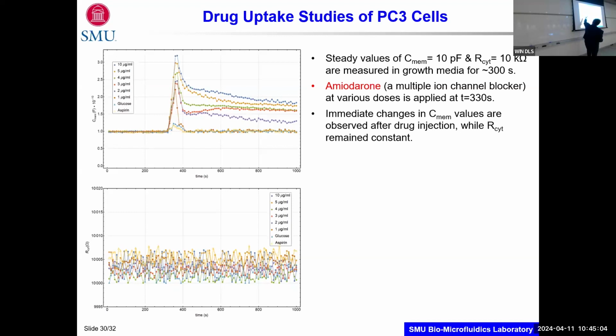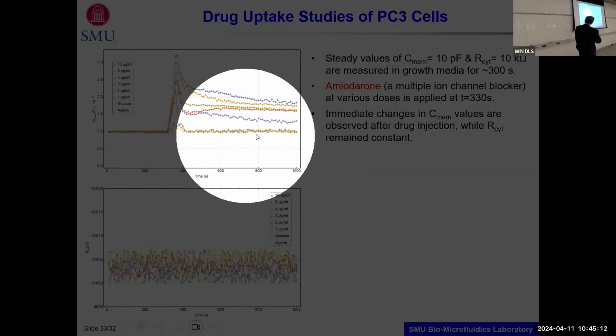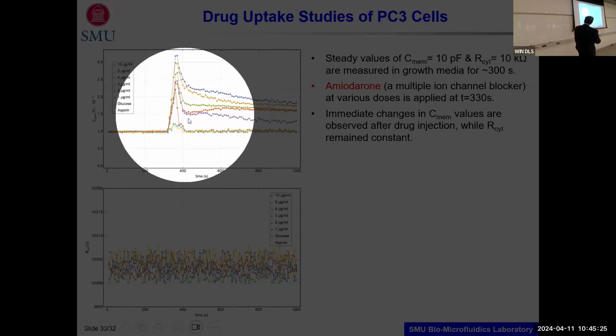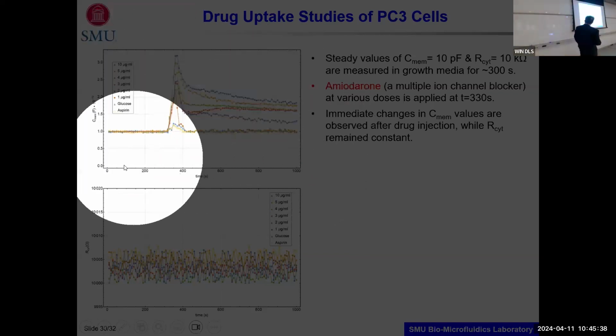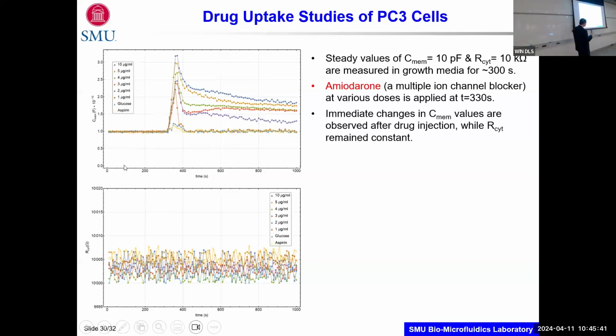in the cytoplasm membrane capacitance. Let's try this again. So this case here is the lowest dose, which actually peaks and then goes to the base value pretty easily. If you increase from 1 microgram per ml to 2 micrograms per ml, you're seeing some transients that probably will reach a steady state. And we did this for like 1,000 seconds. But as you go higher and higher, I think the asymptotes of these are going to change. And I think we have a more permanent change happening in the system.